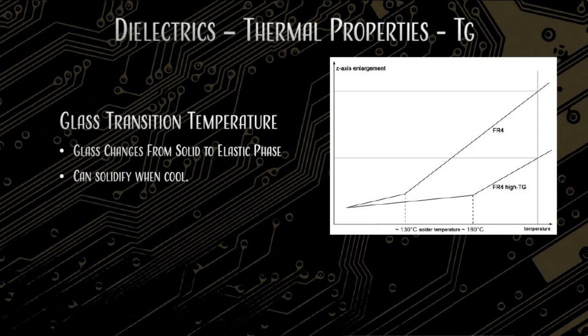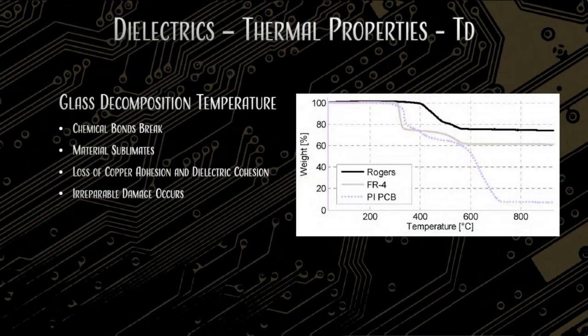We've also got this thing called decomposition temperature, and this is the temperature at which the fiberglass resin mixture loses about 5% of its mass, and it really just starts falling off. This is the point at which it basically starts sublimating or being squeezed out the side of the board. Did you want to tell me about that real quick, Teresa? Yeah. Well, this says irreparable damage occurs at these temperatures. So, I mean, if you put your phone in the oven, it's not going to work. But yeah, you lose copper adhesion, and I've seen boards that have been burned in ovens in manufacturing before, and they literally just dry out. Yeah. And then nothing holds together.